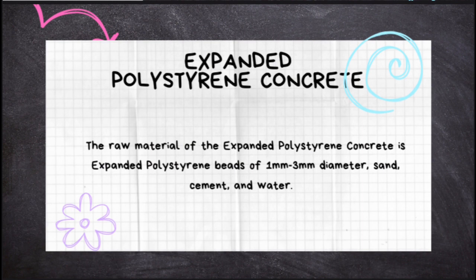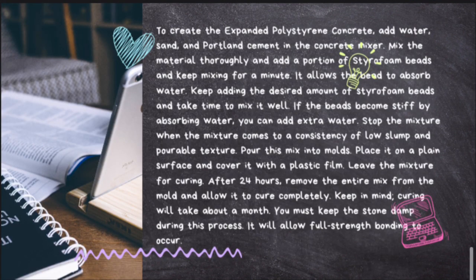The next concrete is Expanded polystyrene concrete. The raw materials of the Expanded polystyrene concrete are expanded polystyrene beads of 1 mm to 3 mm diameter, sand, cement, and water. To create the Expanded polystyrene concrete, add water, sand, and Portland cement in the concrete mixer. Mix the material thoroughly and add a portion of styrofoam beads and keep mixing for a minute. It allows the beads to absorb the water.